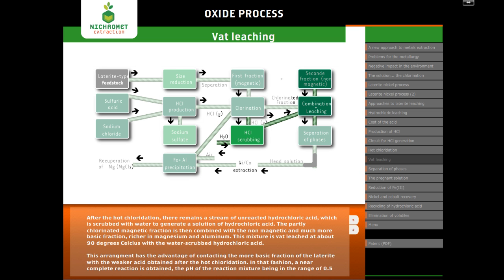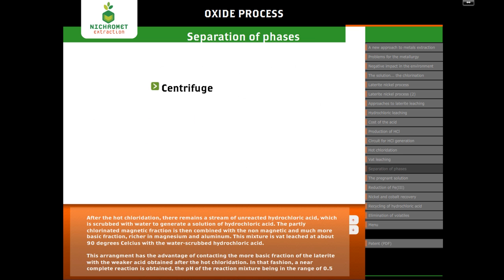In that fashion, a near complete reaction is obtained, the pH of the reaction mixture being in the range of 0.5 to 1.0 after 4 to 6 hours of reaction. After the vat leaching, a separation of phases is needed in order to recover the pregnant solution from the residual solid. This can be done by standard techniques, such as belt filter or centrifuge.